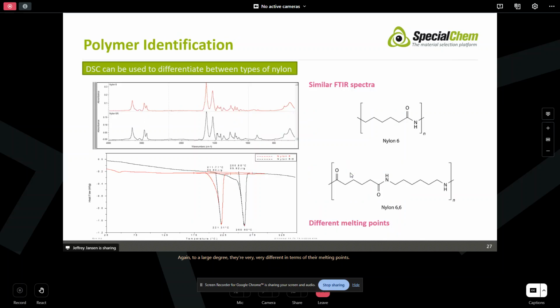In fact, nylon 6 and nylon 6,6, you know, my first technique I usually use in the analysis of polymeric materials is Fourier transform infrared spectroscopy, or FTIR. Well, FTIR doesn't do a good job when the molecules are relatively similar, like we have here with nylon 6 and nylon 6,6. So structures are pretty similar. So the FTIR spectra are very similar, but those two materials have very different melting points. And so nylon 6 melts at around 221, nylon 6,6 around 261 degrees. So again, we can use that to kind of supplement our FTIR. Again, FTIR is a great place to start, but it doesn't give you all the information in all cases. So DSC starts to fill in some of those gaps, helps us with that.